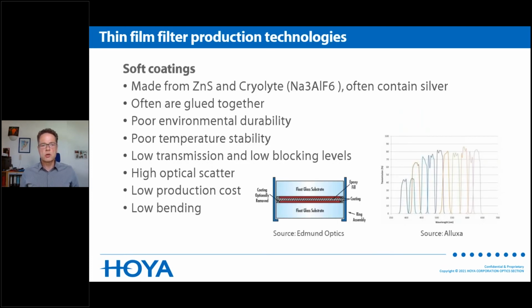Yeah, I mentioned that I want to go through some of the filter production technologies for thin film filters. In the early years of thin film filter production, last century, the soft coatings were used, and they are made from zinc sulfide and cryolite, and often contain thin metal layers like silver. And very often they are glued together from many substrates to achieve the overall filter performance. They typically have poor environmental durability and poor temperature stability. The transmission and blocking levels that are achievable are quite low. Because of the many optical surfaces, you might experience high optical scatter.